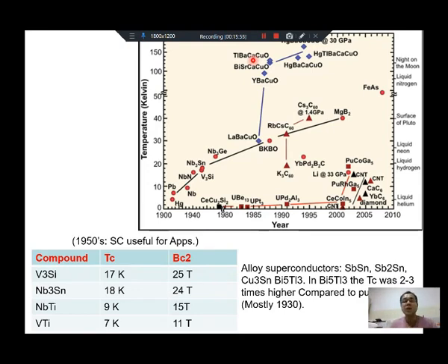Such experiments have been going on in Japan to see the cost feasibility, whether it is actually feasible to do such things, where over kilometers you make such cables, circulating liquid nitrogen through them, and inside have these superconducting cables. Okay, the cost has not been very favorable, there are a lot of issues, as you can understand, in having such complex cables compared to a simple wire which is going to carry current. So there have been issues from the practical point of view in implementing these high temperature superconductors for application.